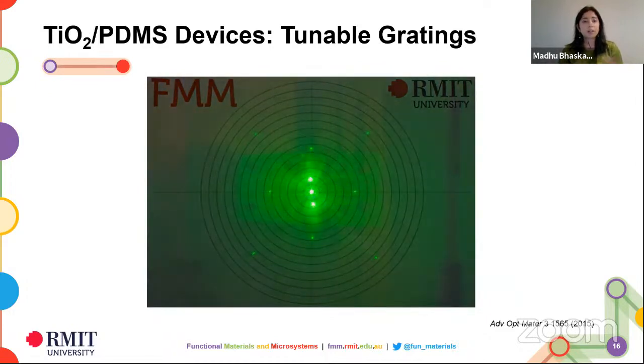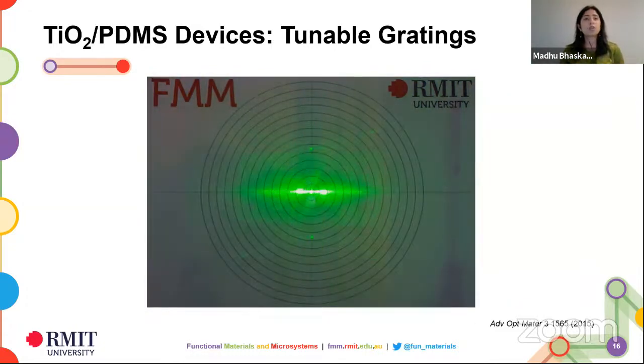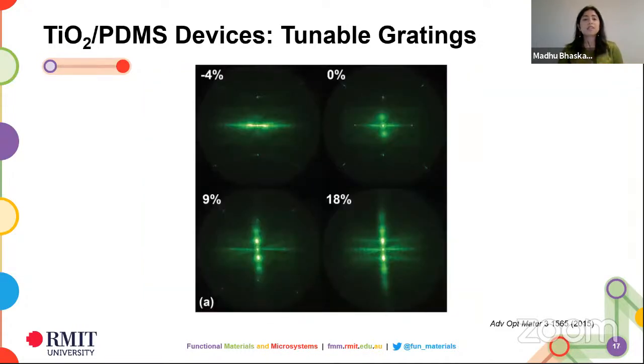So as we stretch the device, you can actually change the diffraction patterns which you get out of these particular devices. So it's quite nice to use these as tunable grating type devices. You can see as you change the strain which you're applying on your titanium dioxide device, you're measuring a change in the diffraction pattern, which in turn relates to the amount of strain being applied. So it's quite nice to create these kind of patterns by just merely stretching the device and thereby lend tunability to your optical devices.